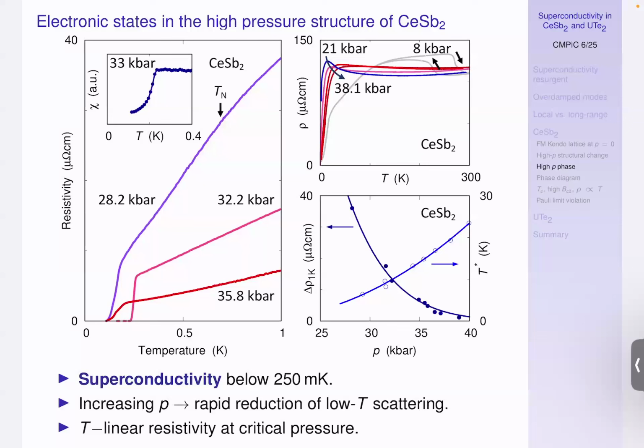It's quite convincing because you can also see it in the susceptibility. It's an interesting material because everything happens at such low temperatures. It has, in the lingo, a very low Kondo temperature. If you look at resistance versus temperature on the big scale, at about 30 kilobar the resistivity is basically flat from room temperature down to about 10 Kelvin, and then it collapses. Most of the change is actually below 2 Kelvin. Going from 0 to 1, we're already up at 40 micro-ohm centimeters, which is about a third of the full resistivity. So everything is a very low temperature material. And like many of these materials, it has a linear in temperature resistivity at the critical pressure.